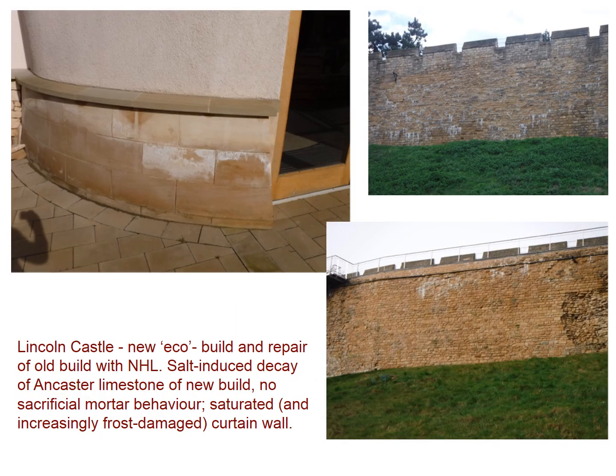But equally, we see similar behavior in NHL mortars. Lincoln Castle, a new eco build and repair of an old build with NHL. Salt-induced decay of Ancaster limestone in the new build 2 years after construction. No more sacrificial mortar behavior. The curtain wall of the castle, on the other hand, saturated and increasingly frost damaged, with chunks of stone having to be picked up on a daily basis in midwinter.